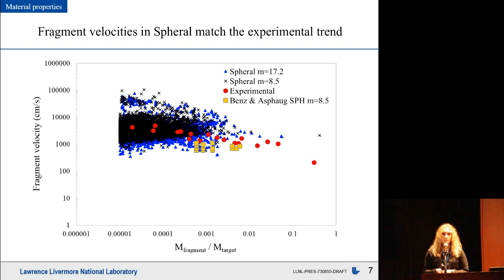What we find for our spheral results shown in blue and black is that there's a girth of fragment velocities for the smaller fragment masses, sandwiching the experimental trend line shown in red.